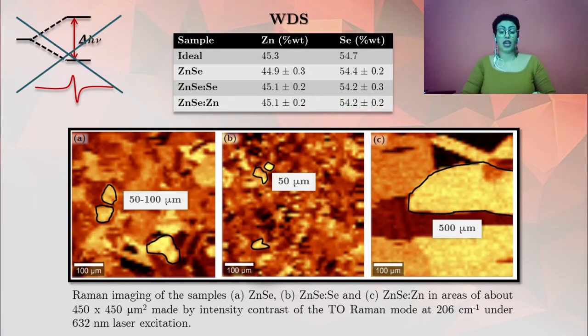of their grains. Quantitative microanalyses were performed by wavelength dispersive spectroscopy, and impurities were not observed, confirming the ultra-high purity of the samples. Comparing the mother samples with an ideal zinc selenide stoichiometric crystal, the quantification shows that there are no significant stoichiometric differences between the samples within the uncertainty of the measurements. The high purity and low deviation from stoichiometry of the samples are characteristic of the CVD growth method, even with a significant excess of one of the components during the growth. And this can be the reason for the non-observation of EPR signals.